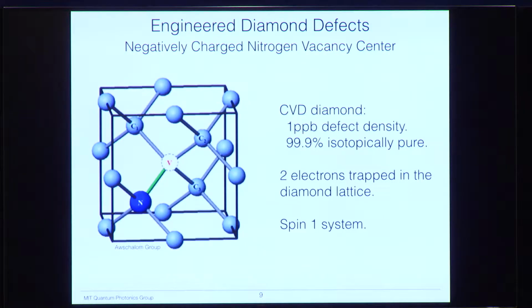The system that I will talk about during this talk is the negatively charged Nitrogen Vacancy Center in Diamond. Before I talk about what the NV Center is, first I'm going to talk about why Diamond is so good. The reason is basically that we can produce more or less perfect CVD, chemical vapor deposition grown diamond. We can create this diamond such that it is almost completely pure, so fewer than 1 part per billion defects in the diamond to begin with. And it can be isotopically pure as well, so there are no carbon spins to complicate the situation, or very few at least. Then how we create the NV Center is we replace one of the carbon atoms with a nitrogen atom, and next to it is a vacancy. And this creates a trapped 2-electron system, or a spin-1 system, that we can use for quantum information processing.